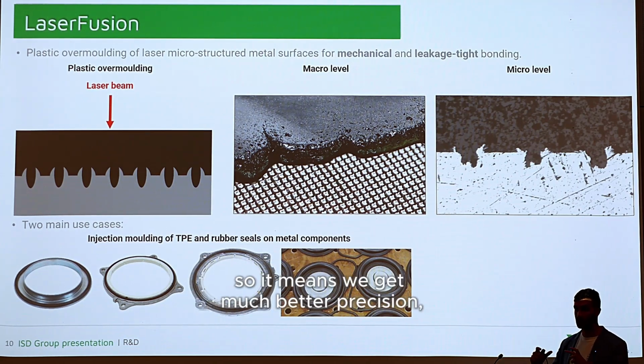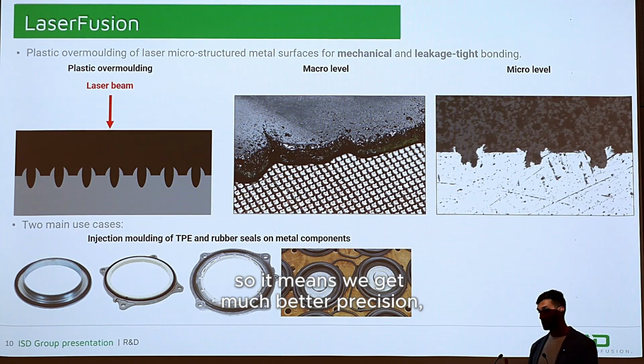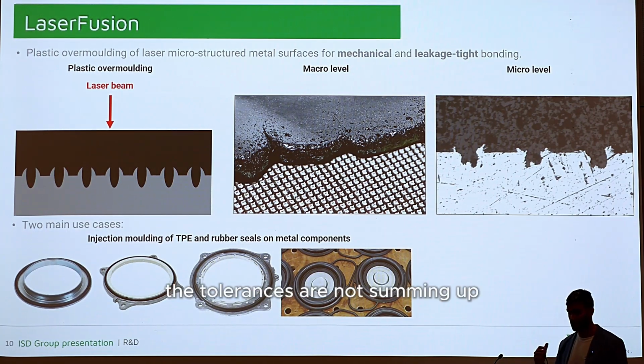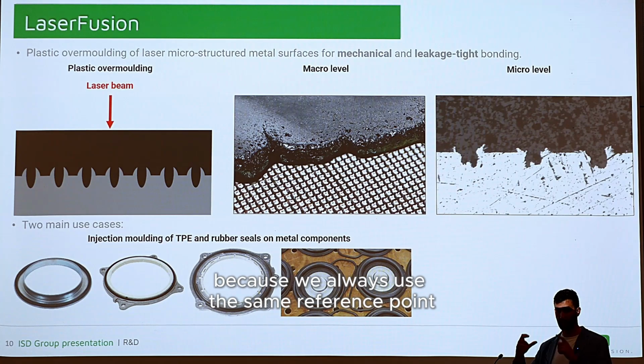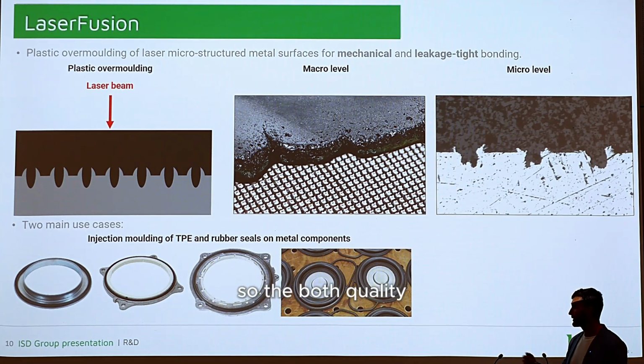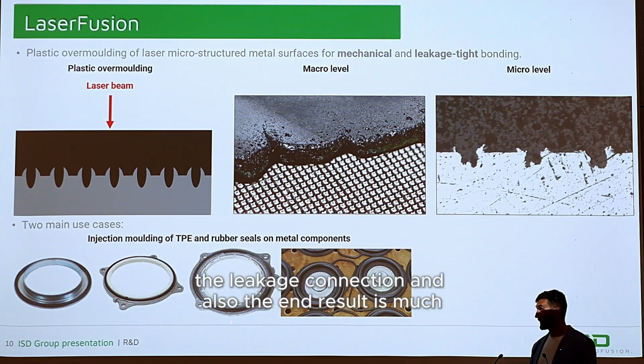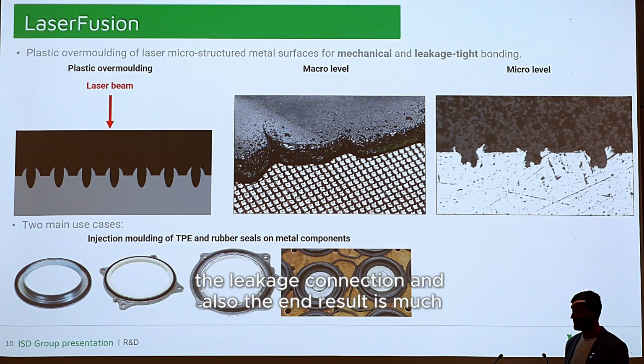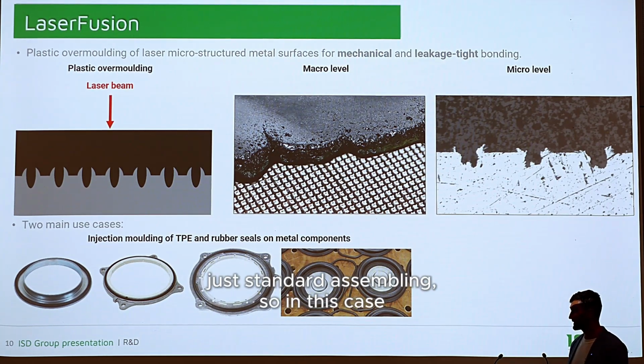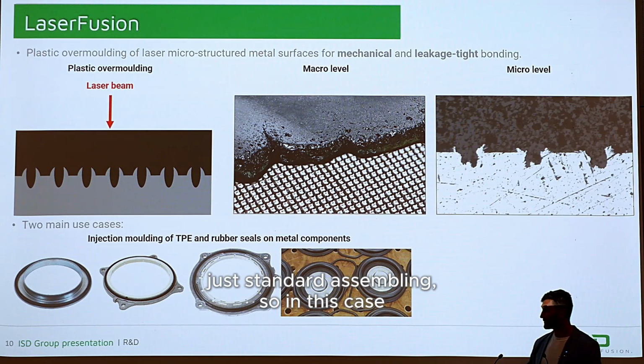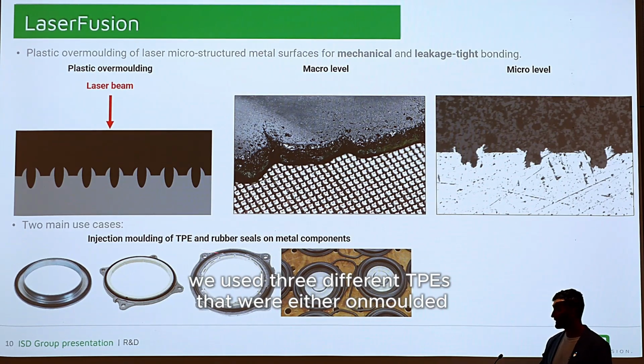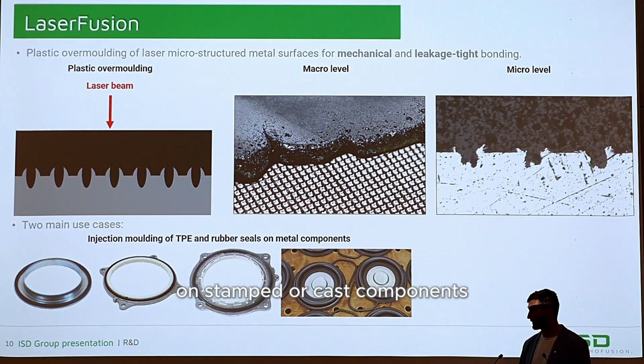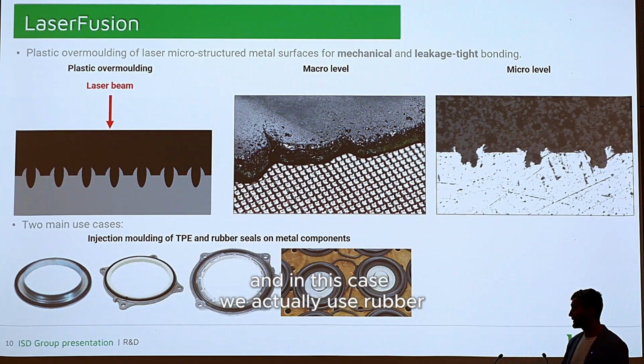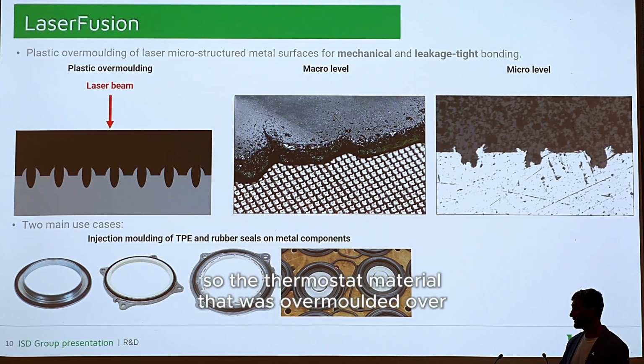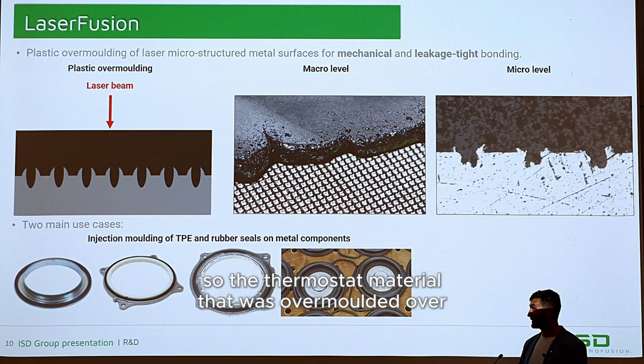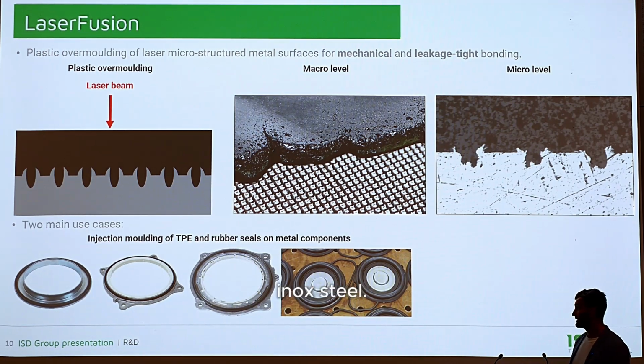So we get much better precision. The tolerances are not summing up because we always use the same reference point. So both the quality, the leakage connection, and the end result are much better than with standard assembling. In this case, we used 3 different TPEs that were either overmolded on stamped or cast components. And in this case, we actually used rubber, a thermoset material that was overmolded over inox steel.